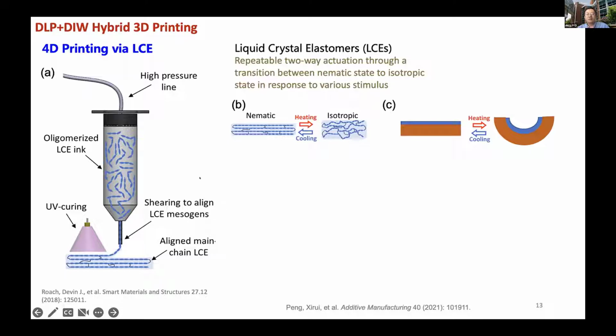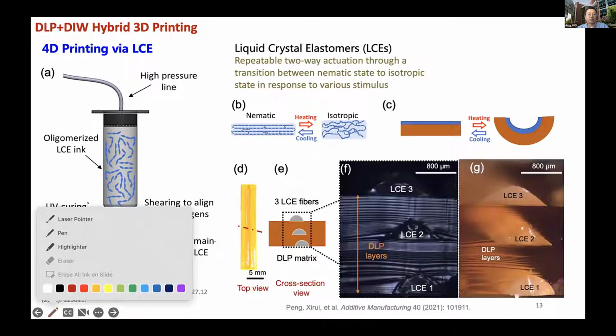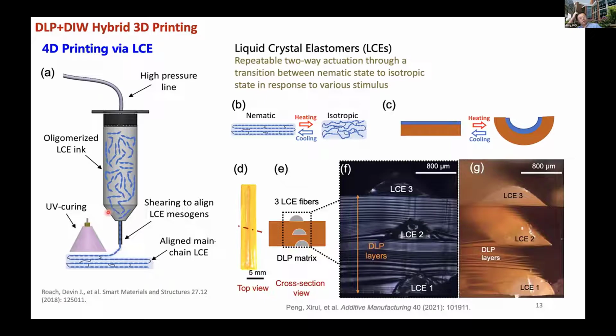So DIW actually is perfect for printing of liquid crystal elastomer because the shear effect during the extrusion can align the mesogens. So DIW is the most efficient way nowadays in printing liquid crystal elastomers. With this approach, we can integrate liquid crystal elastomers into our DLP printing structure. So then we're using the DLP to print a large box structure with high resolution, and then we write LC ink inside it, and then we can either embed it or we just leave it on the top.